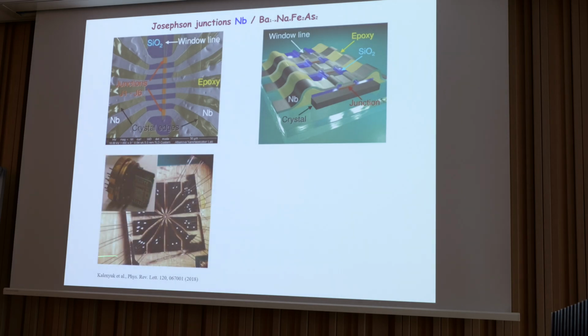So this is how it looks on a larger scale. We have electrodes, bonding, and then put it in the crystal. This multi-contact configuration of our sample allows us a variety of measurements. We can, in fact, measure the in-plane transport as well, by sending current from one junction to another and measuring voltage responses on other contacts.